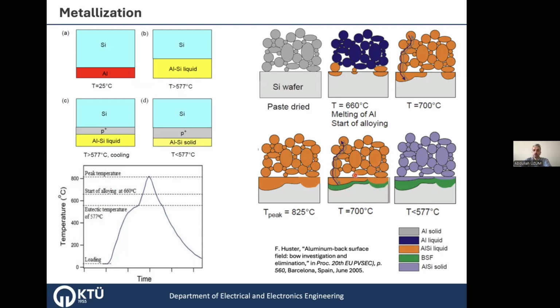So again, this is the aluminum case, which is very similar to the front case. And in practice, what we do is screen print aluminum on the backside, dry it, and then flip over the wafer, screen print the silver on the front side, and then dry it. And after that, both of them go through the same profile like this for what we call firing.